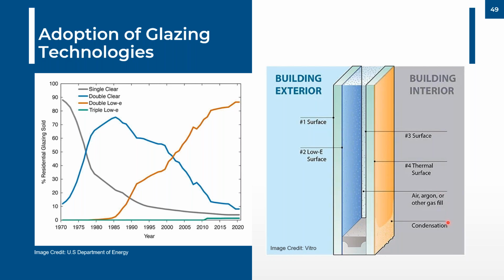What happens with this technology is it reflects the heat back to the inside, creating a lower U factor. Now, because it's reflecting heat back to the inside, that heat does not have a way to warm the perimeter seals here, which causes those seals to actually get cold from the outside during wintertime conditions, especially on those really cold nights. And because that's getting cold right here, you have a higher likelihood of condensation with this solution, condensation building up many times at the bottom of the glass right here. And long-term condensation can lead to more problems down the road, such as mold buildup and other problems.